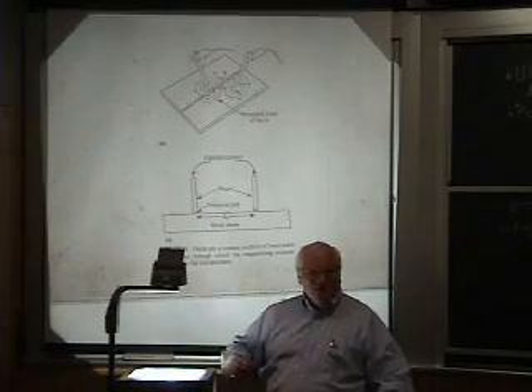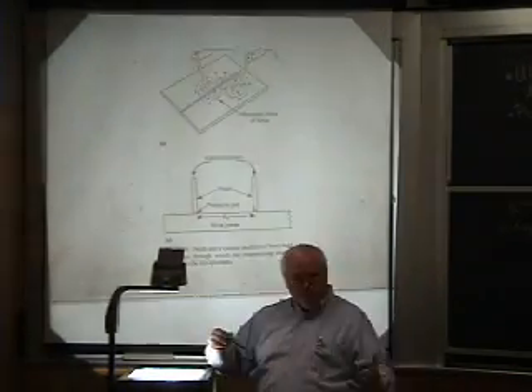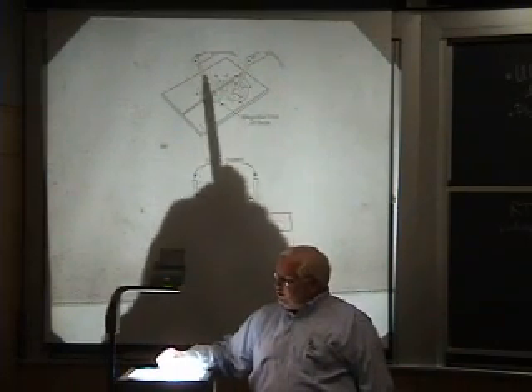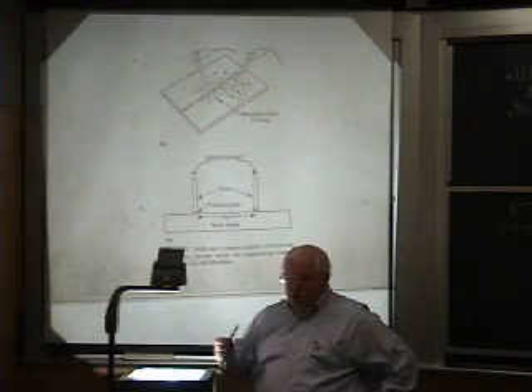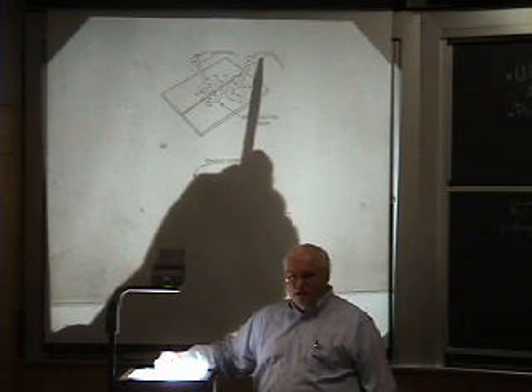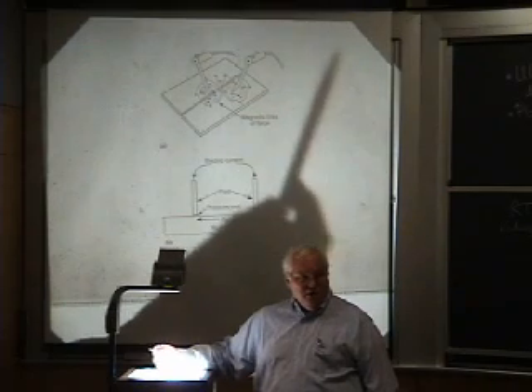Well, to magnetize something in the field, you can't just clamp it in this lathe in the shop, but for small parts in the shop, this is a very effective technique. In the field, you may go with what we call prods, and basically you just have a power supply. It's much lower voltage than a welding power supply, but it's very high current. Some of these things will put out 10,000 amps for really big pieces of equipment. You need lots of amps in order to get magnetic saturation on big heavy pieces of steel.